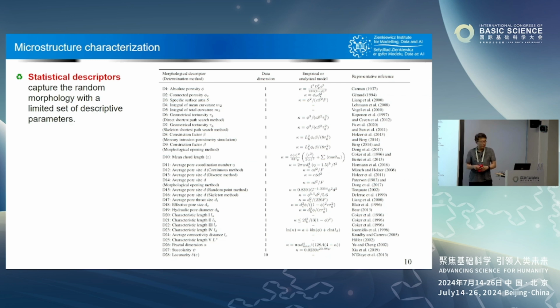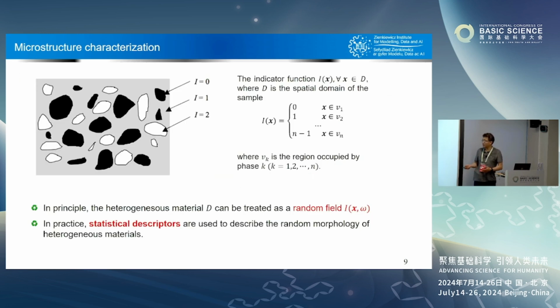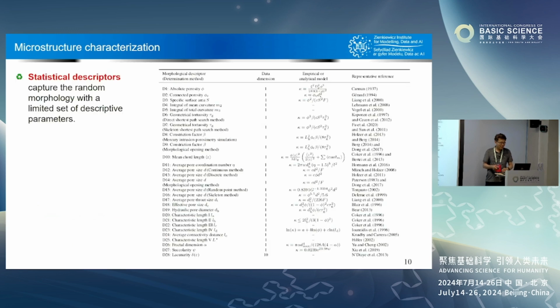And then you have a field like composite materials, chemical engineering, even tissue engineering in medicine. They have defined their own descriptors. Some of these overlap a bit, some of these are totally different from each other. Overall, we might say we have 150 to 200 statistical descriptors. Of course, none of these works individually. You have to put them together, take a combination of them, and still they wouldn't even give you a comprehensive quantification of your random field. The only way to capture a random field comprehensively is to go for the joint probability distribution. Or you start to introduce assumptions. Let's say if it's a one-dimensional thing, you say it's a Markov process, which again is very rough and never works with real material.